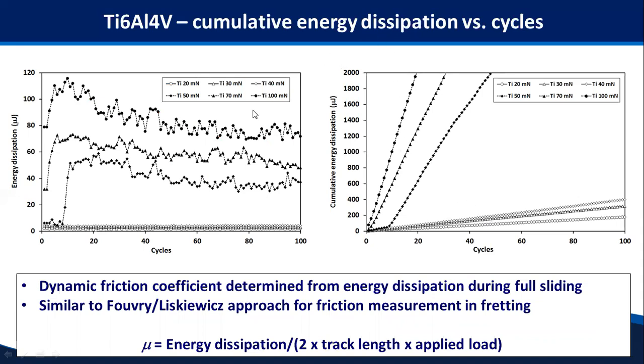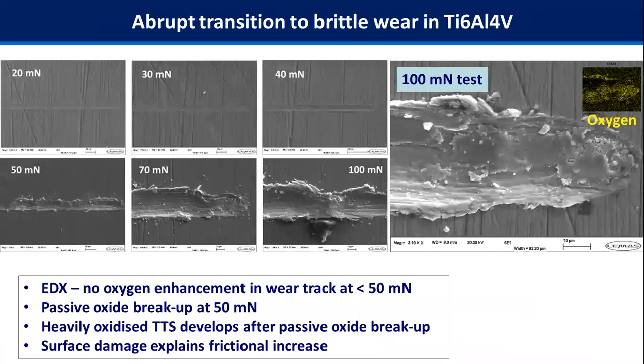And we just want to mention that when we look at the friction coefficient, we're actually recording the dynamic friction coefficient. So this is the friction coefficient under full sliding. So what is behind this? Well, at 40 millinewtons, the passive oxide that protects the underlying titanium alloys is not worn away by the 100 cycles in the test, and there's no oxygen enhancement in the wear track.